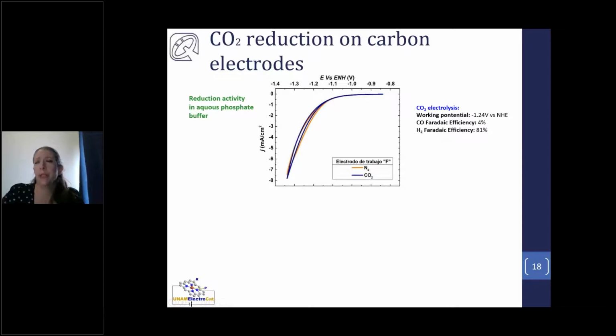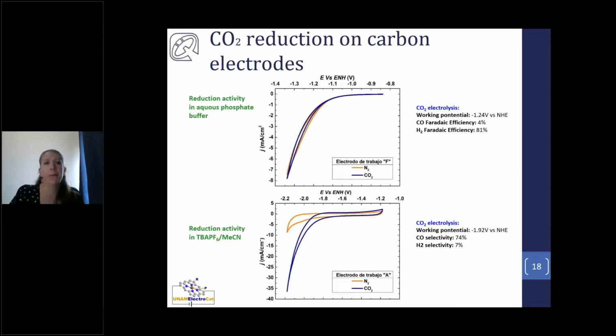But then for the other project, we started working also with acetonitrile, and what we saw was quite different. In acetonitrile, when we do the cyclic voltammetry in the presence of CO2, we see quite an important reduction current. This is an indication that carbon paper can actually reduce CO2. Keep in mind that we're going to much more negative potentials than in aqueous electrolyte. But nevertheless, when we analyze the product, we see clearly that these carbon electrodes are selective towards CO production.